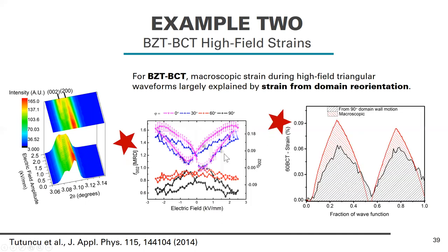Now, if we take this data and calculate the net effect of switching to the macroscopic strain, we can see the macroscopic strain plotted over here as the red line, and then the contribution from domain switching as the black line. And so in this material, that's not exactly at the MPB, but it's compositionally close to the MPB, we see a significant contribution of switching to the macroscopic strain.